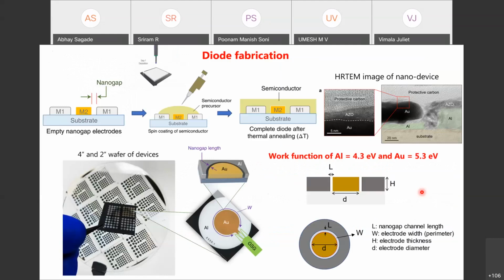So now once you have this set of electrodes on a substrate, then you can deposit your semiconductor on top of it by any of the deposition techniques. The technique which we selected here is the spin coating technique.